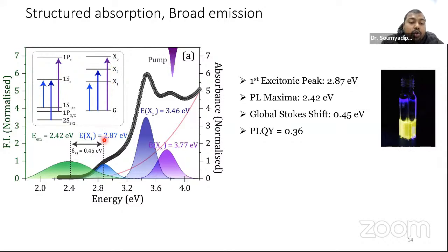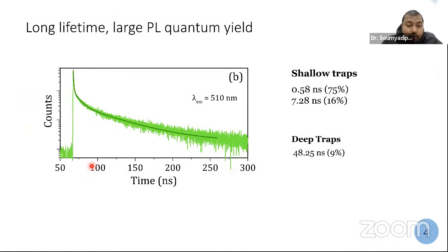When we excite at 2.87 electron volt, we get a broad emission. Although it's a greenish yellow emission, it's not sharp like CdSe or CdTe; the FWHM is quite high. It was already known that in water-soluble quantum dots, surface traps play a very major role, so the surface traps and other things give a broad emission structure. The PL transient shows three times: a very fast decay of 0.6 nanoseconds, which is 75% of the amplitude, and others at 7.3 and around 50 nanoseconds. This can be ascribed to shallow and deep trap states of the quantum dots.